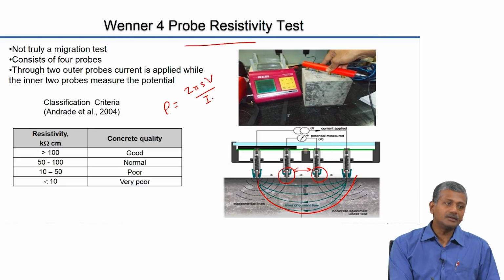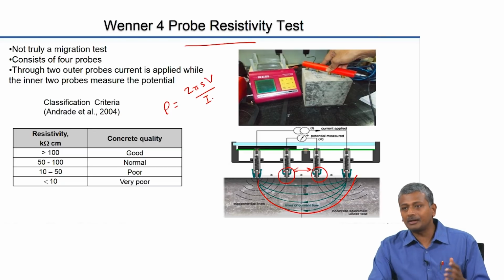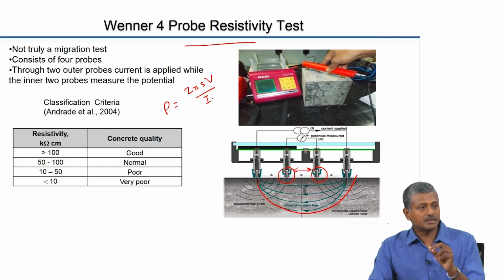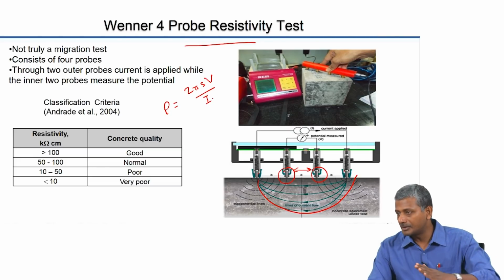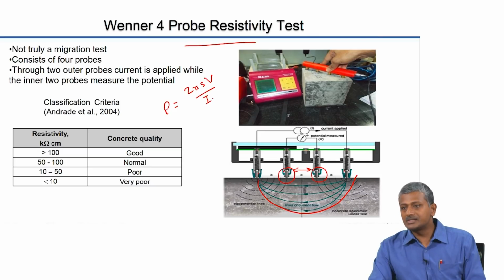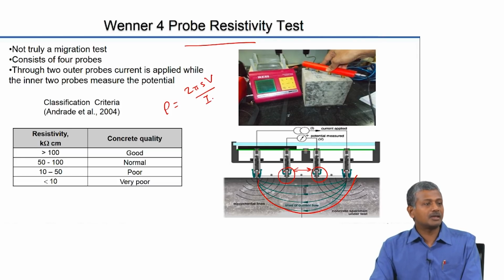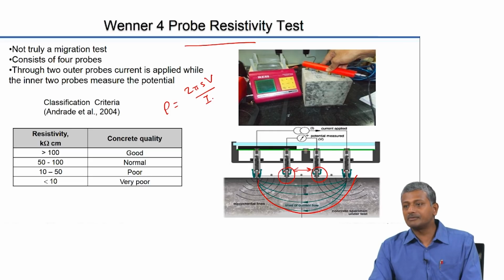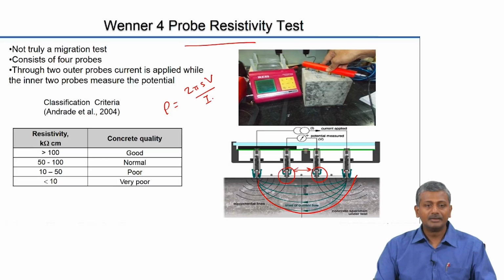Now, resistivity, you know very well that concrete is going to be conducting through its interconnected porosity. When there is interconnected porosity, only conduction will happen. Okay? So, resistivity is the opposite of conductivity, right? So, if the concrete has a very less amount of interconnectivity of pores, the resistivity is expected to be high. That means a durable concrete will have a higher resistivity.